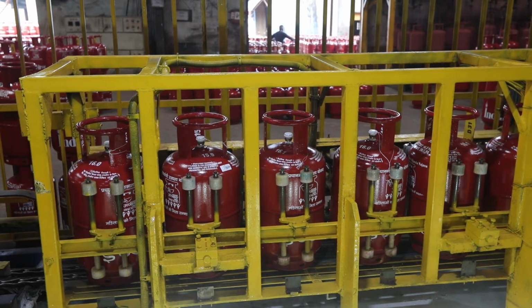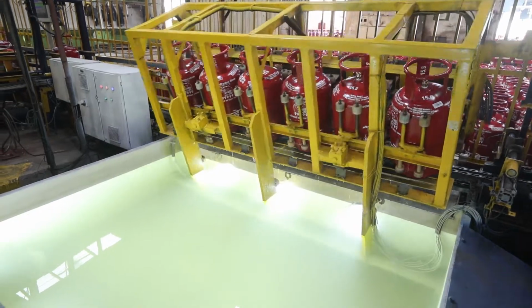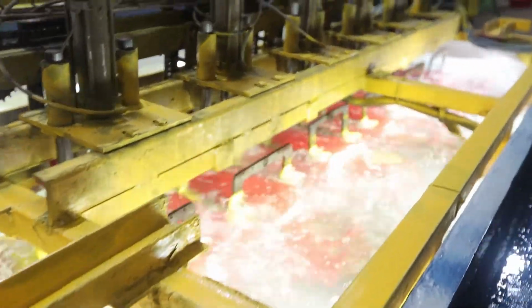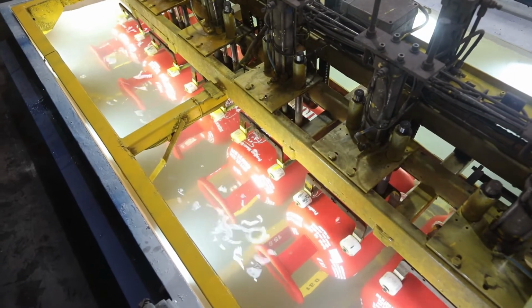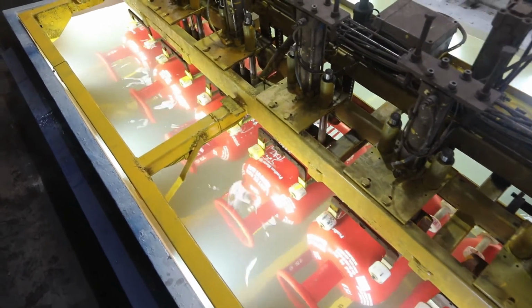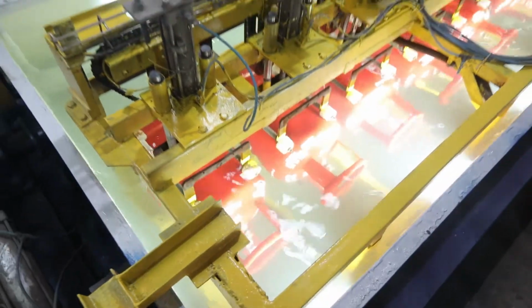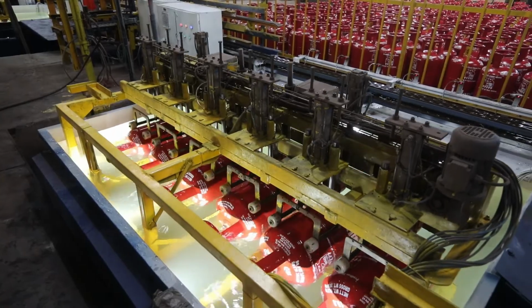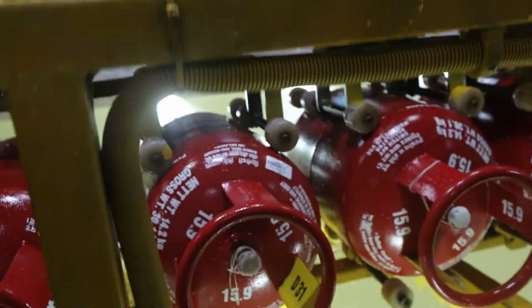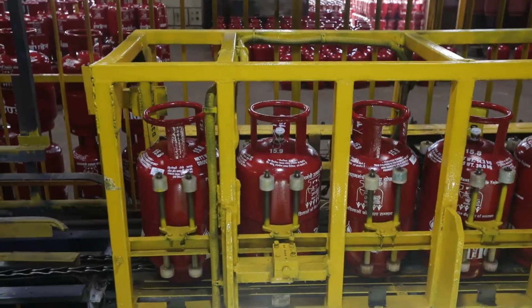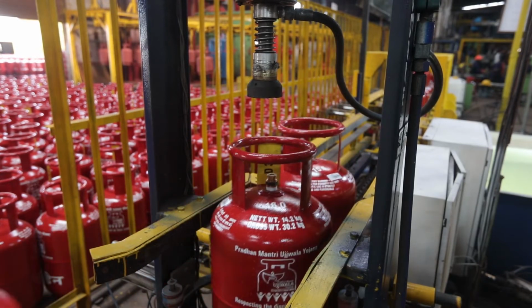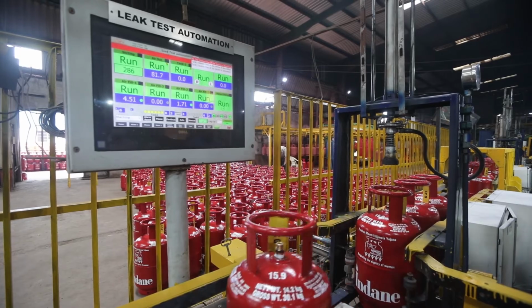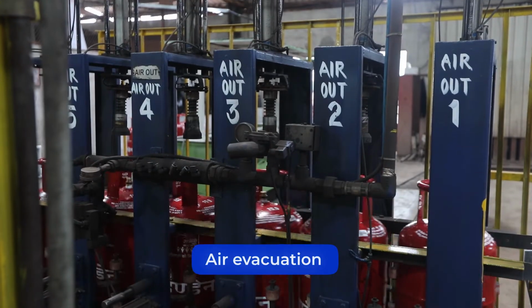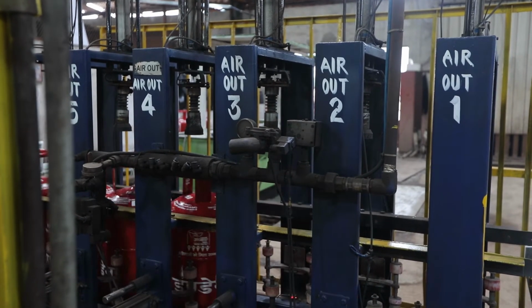Step 1. The pneumatic leakage test is carried out only after confirming the test pressure. Step 2. Such cylinders are then immersed in the clean water tank for 1 minute, duly illuminated from outside and inside of the testing unit. Step 3. After the standstill condition of water, the cylinders are kept immersed in the water tank by a pneumatically operated cylinder, holding the fixtures for 1 minute. Step 4. Cylinders that successfully pass the test are sent for air evacuation and further operations. Cylinders that get an OK from pneumatic leakage tests are then taken for air evacuation. The operation is carried out with the help of air regulators.